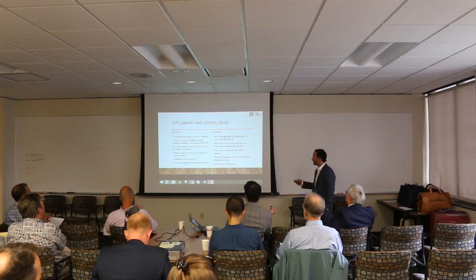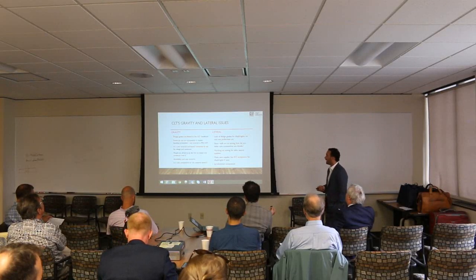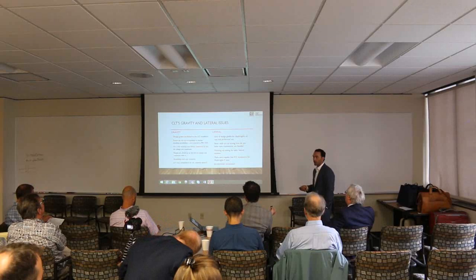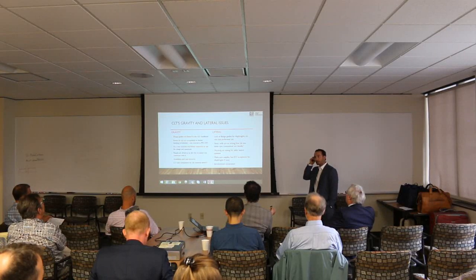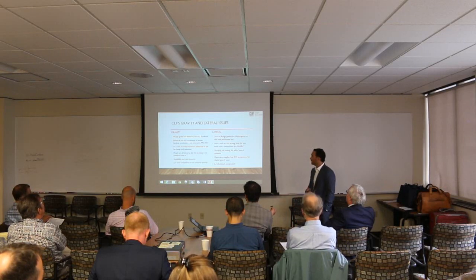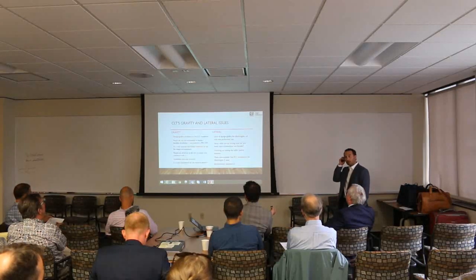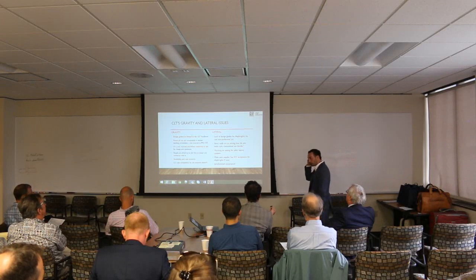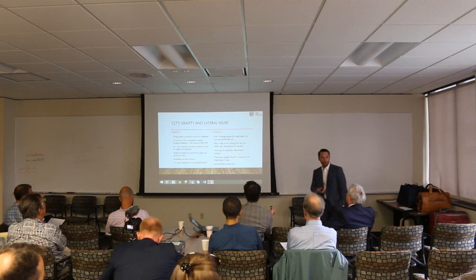Laterally, you have some of the same issues where there's a lack of design guides. And in fact, for diaphragms, I'm under the understanding that there's no real full-scale test performed to back up some of this stuff. There's a lot of good methodologies of how to design diaphragms and design guides and white papers for it, but really, to date, there's no true test for it that I understand. Laterally, the shear walls, they are very strong, but that's also a drawback in how you address ductility issues. How do you make the failure become ductile before the wood splinters and it's a brittle failure? So there's ongoing research on that, which I think we'll hear a lot more about today.